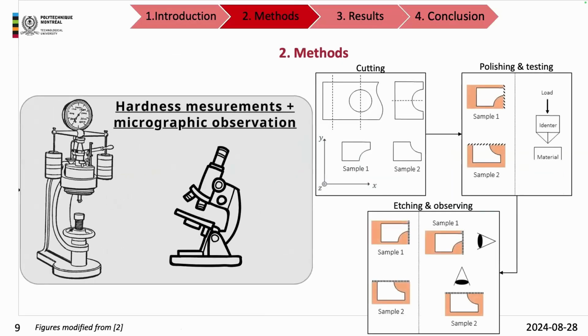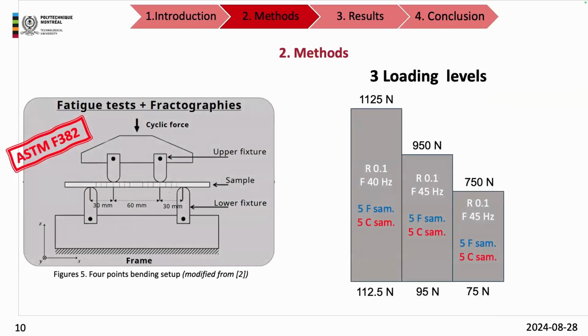Here, I just wanted to share with you the fact that we performed hardness tests and microstructure observation following transversal, here with sample 1, and longitudinal with sample 2 observations. Regarding the fatigue test, as I told you, it's a 4-point bending test following the ASTM F382, and we performed the fatigue test at 3 loading levels. And for each loading level, we studied 5 specimens per manufacturing process.